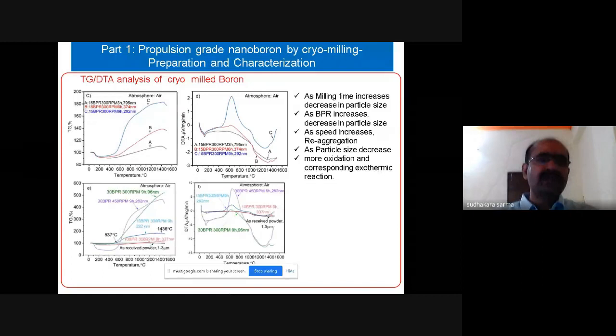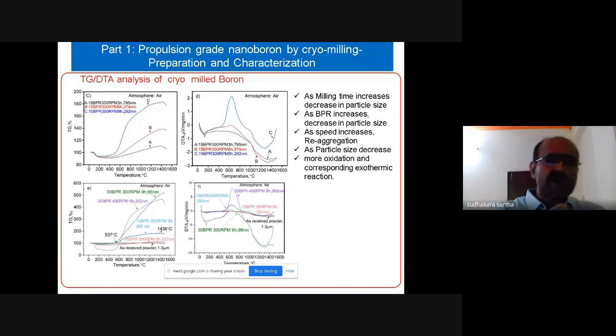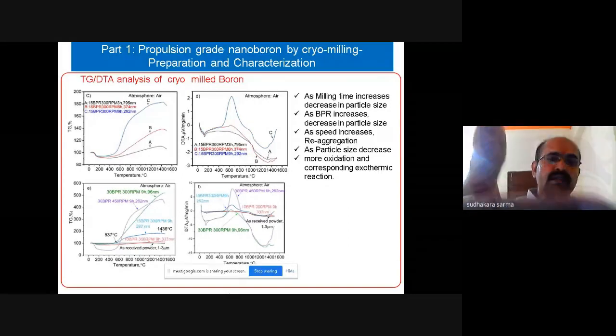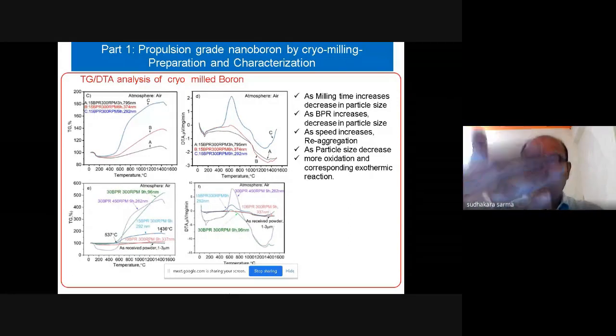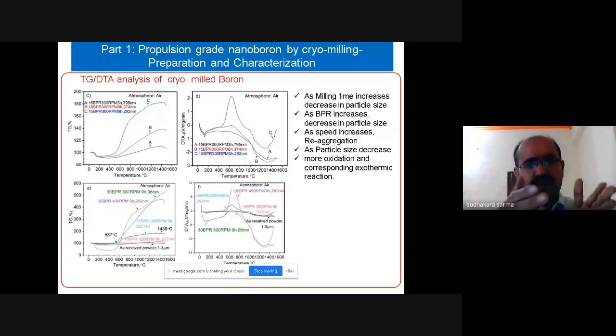That is A, B, C. A is 3 hours milling, and B is 6 hours milling, with 374 nanometer particle size, and C is 9 hours milling. The particle size is 292 nanometer. That means with increasing milling time, the particle size is less, and with that the mass gain is more. So with the decrease in particle size, more mass gain.